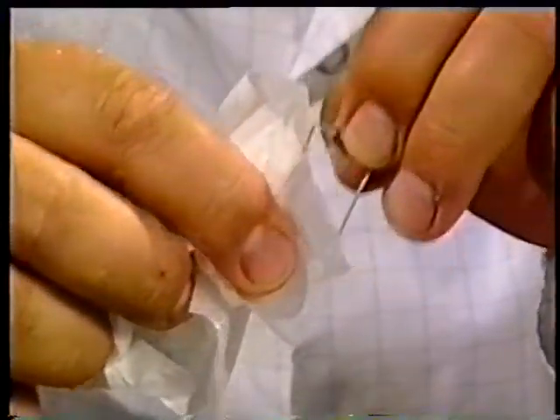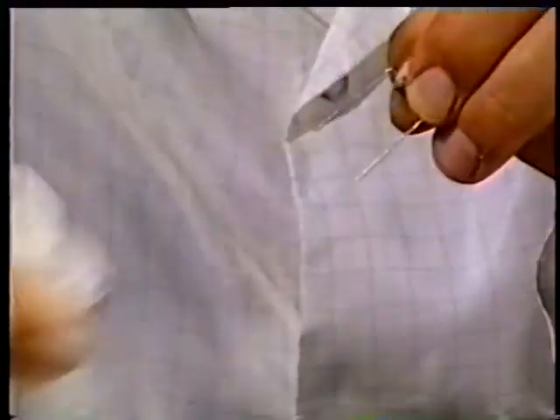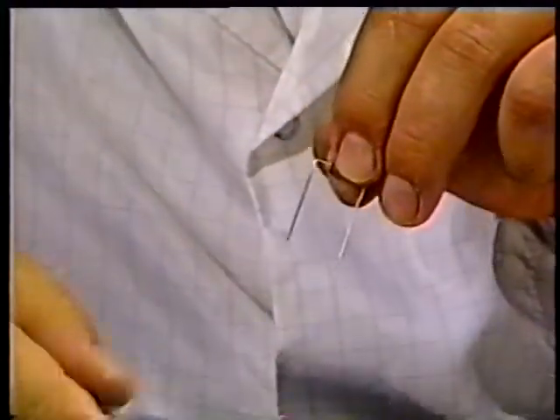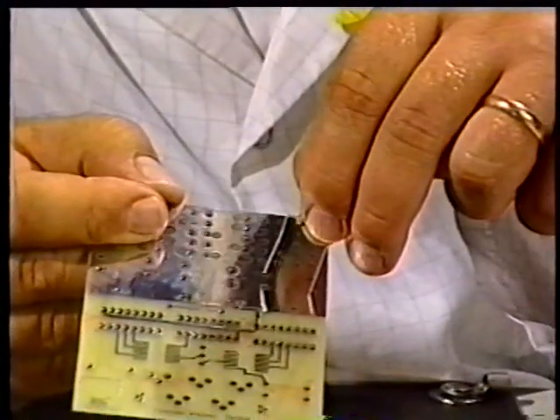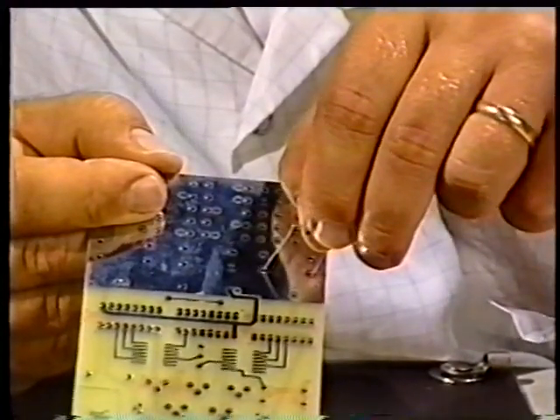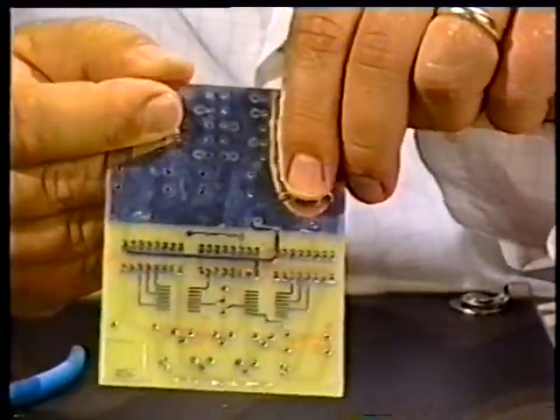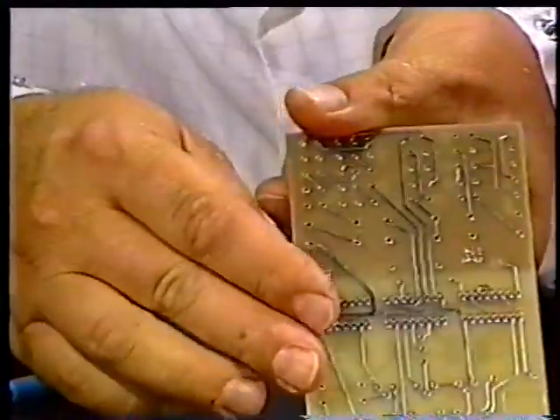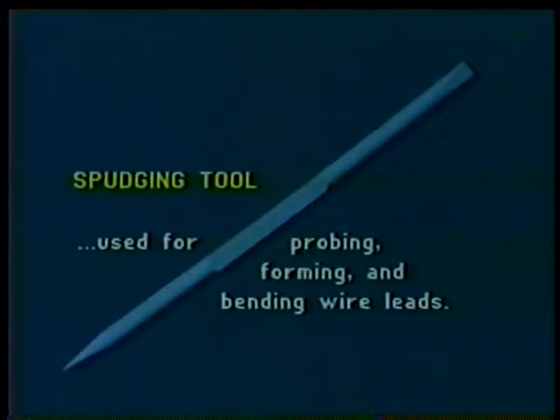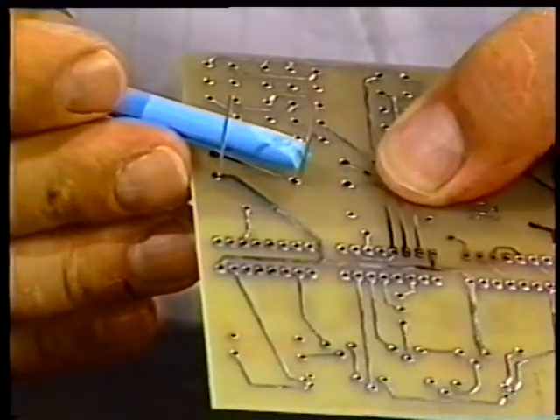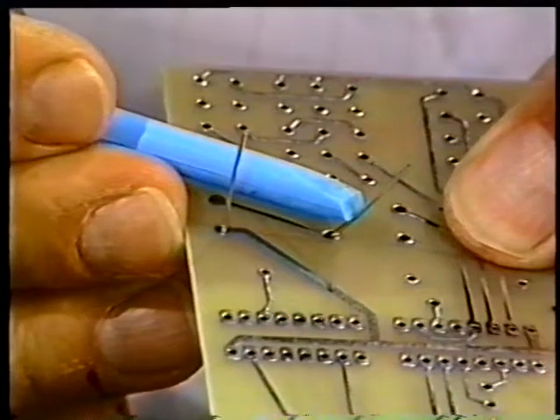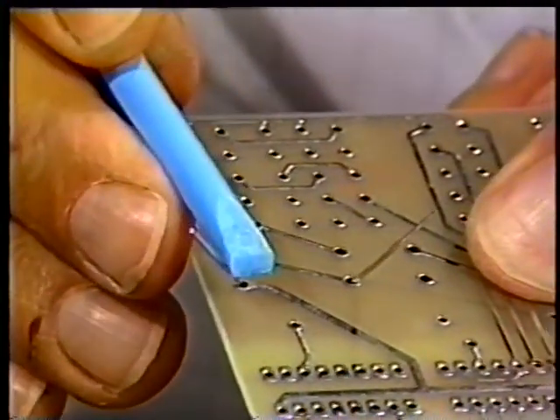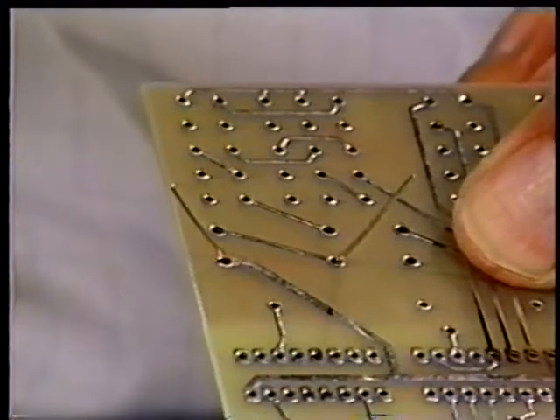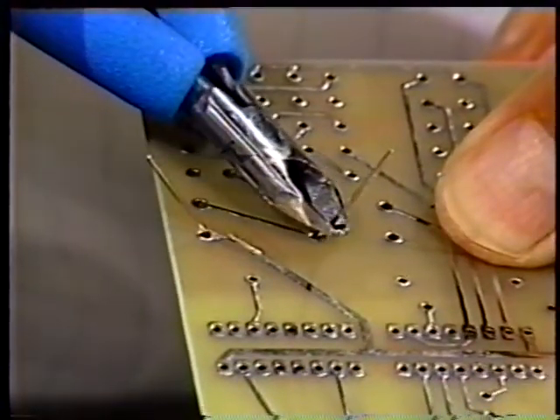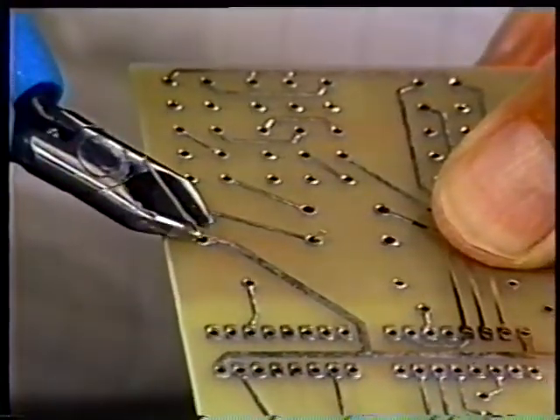The leads are wiped again to remove any oils transferred from the fingers. A non-metallic spudging tool used for probing, forming, and bending wire leads is employed here to make half clinches on the component leads. The half clinches will hold the component to the board during the soldering operation. The leads are cut before the joints are soldered to reduce possible shock damage to the joint.